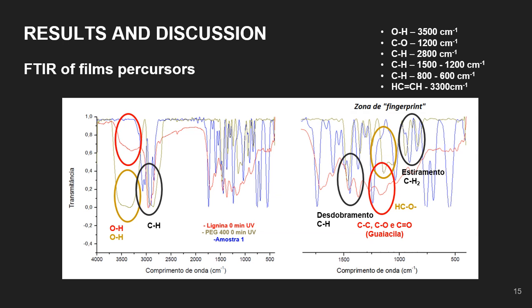This slide shows the spectra obtained from the FTIR analysis of the film's precursors, which are superimposed in order to establish an idea of which bands may or may not be altered in the matrix, such as the appearance of the lignin hydroxyl band and PEG-400 around 3,500 cm, as well as carbon and oxygen bonds around 1,200 cm, such as widening or narrowing of the bands of splitting or stretching of hydrocarbons.